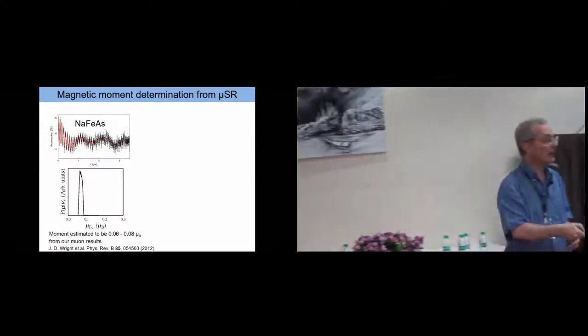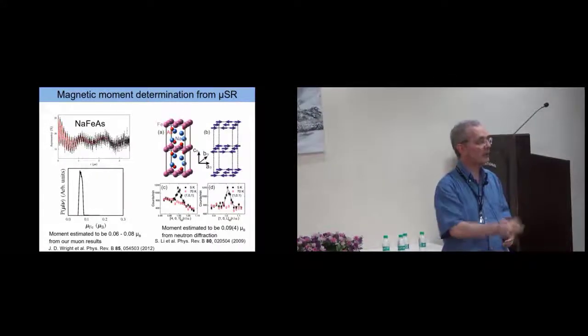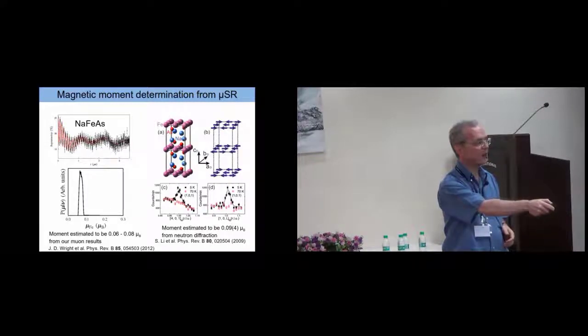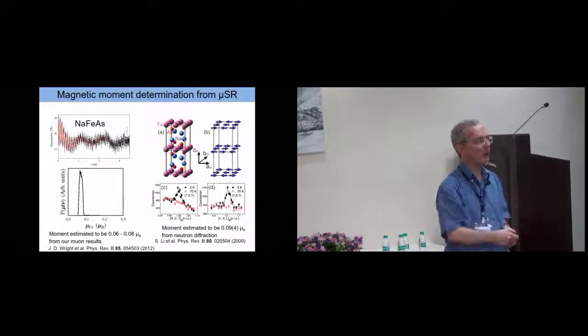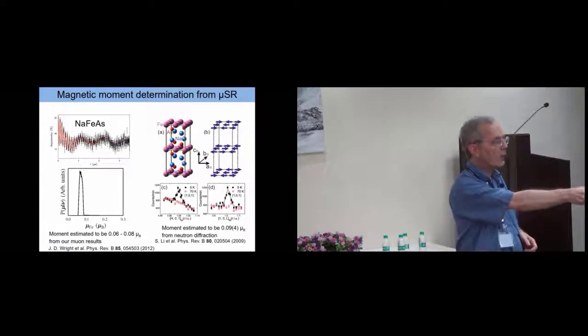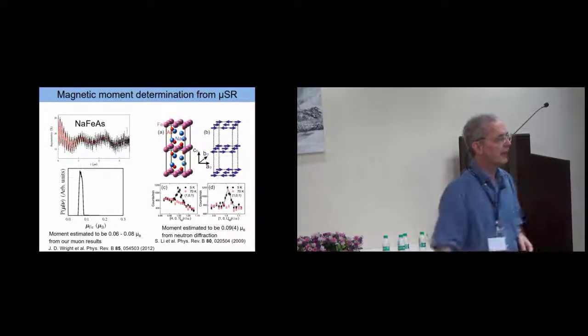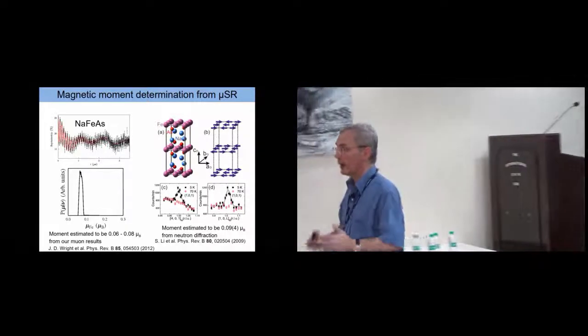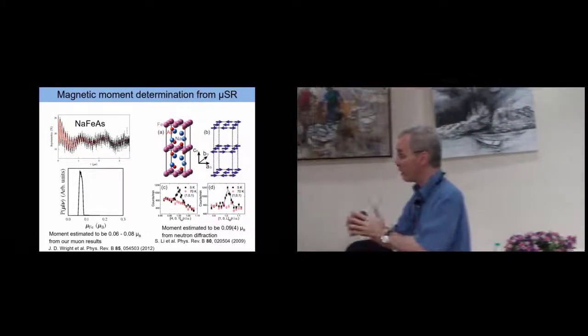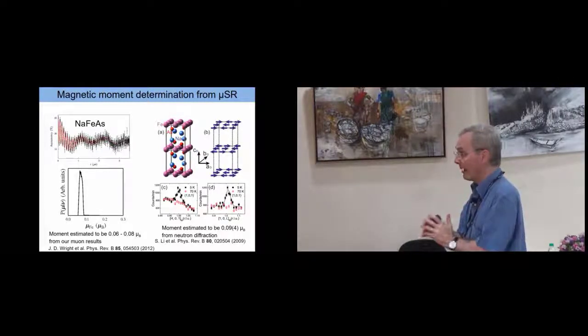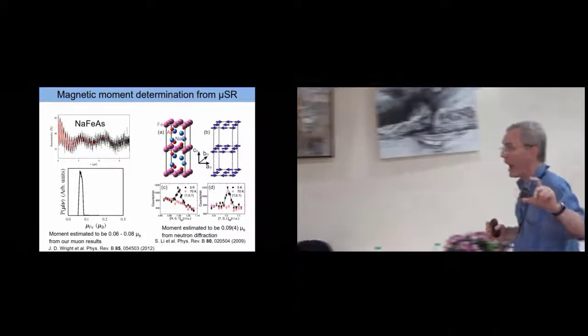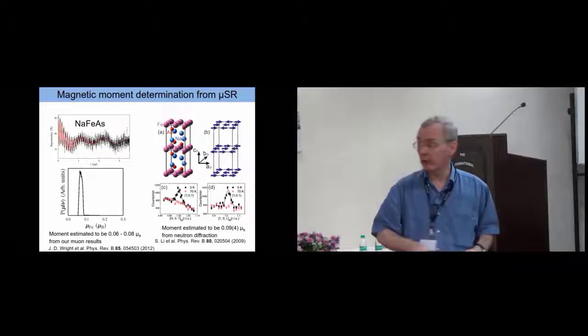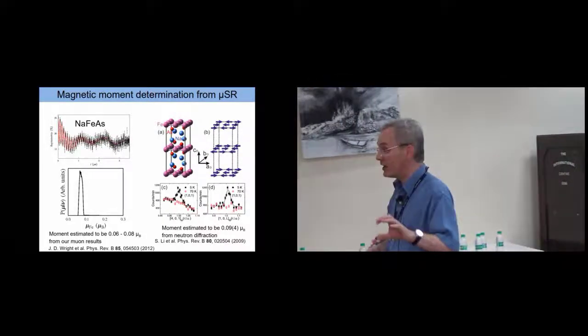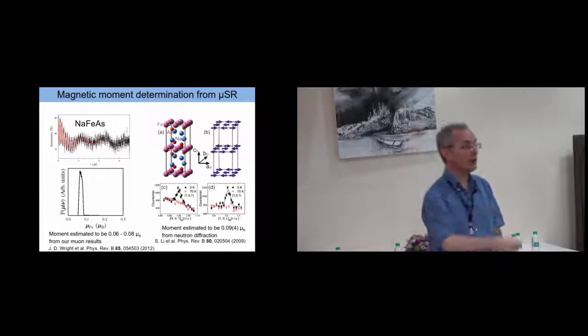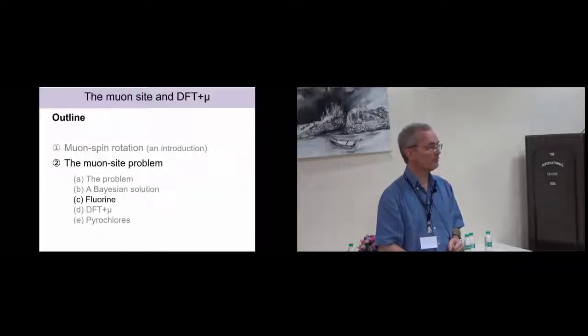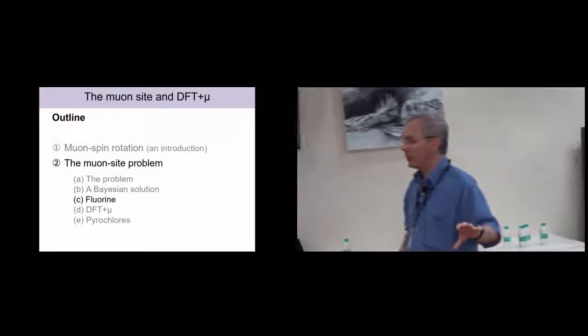Now, it turns out that in this particular material, it could also be measured using neutron scattering, and they get 0.09 plus or minus 0.04. But intriguingly, of course, with such a low moment, this is quite hard to measure with neutron scattering because the size of a magnetic peak goes with the square of the moment. So small magnetic moments are very hard for neutrons to measure accurately. Even with total ignorance of the muon site, we get quite a good value in agreement with the neutron scattering from this approach. Okay, so that's the Bayesian solution.